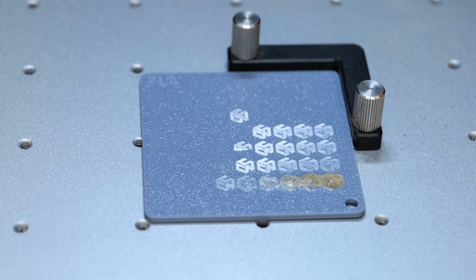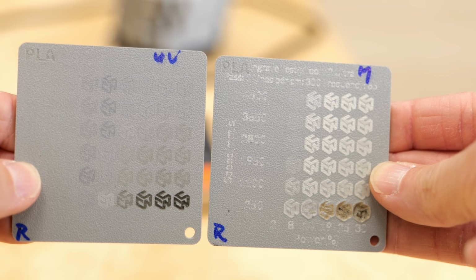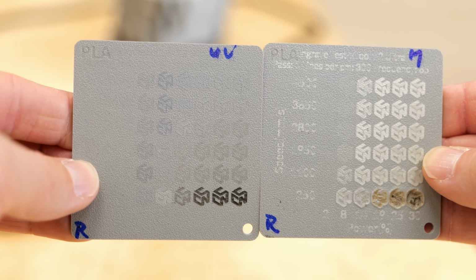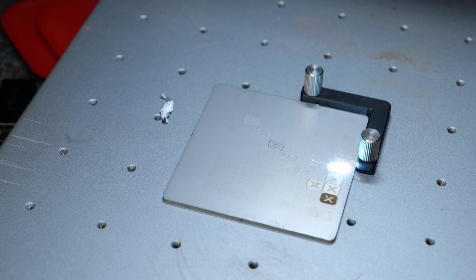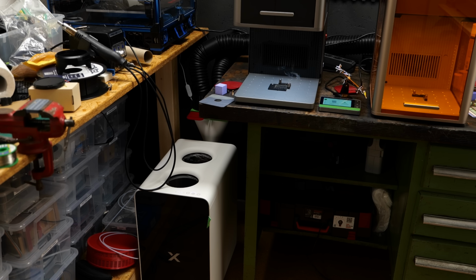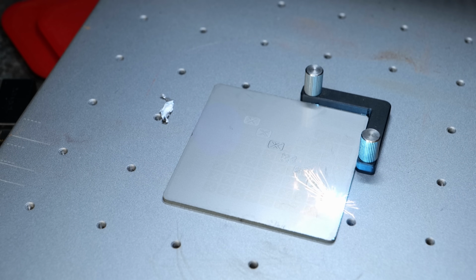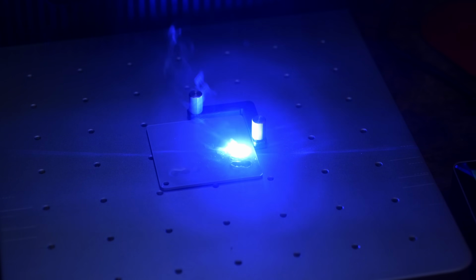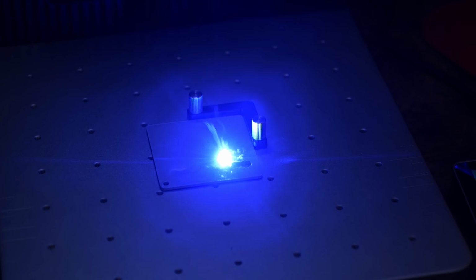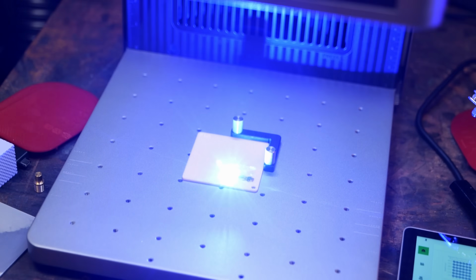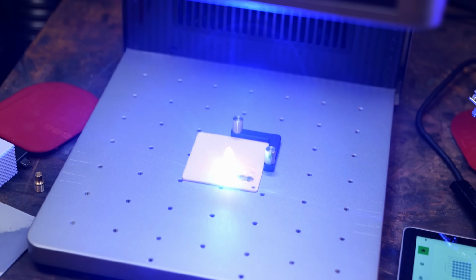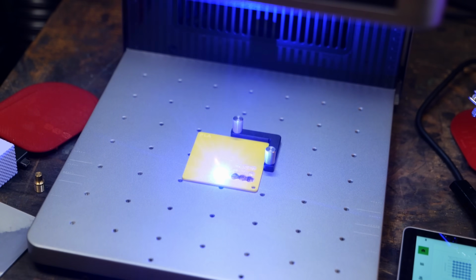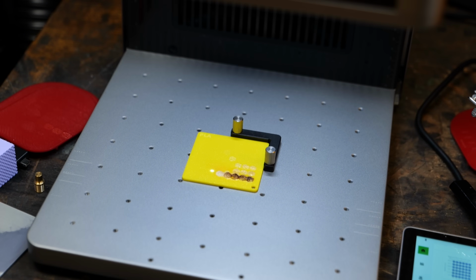The MOPA laser was also very capable, and on some materials it worked even better than the UV laser, but it is clearly more a metal marking machine. And for plastics, the 60-watt version often has way more power than you really need. The big advantage though is the extra control over pulse duration and frequency, which gives you more ways to tune the interaction. The blue diode laser was the least useful for cleanly marking plastics in my test. It can mark or melt some plastics, but the process window was much narrower, and it often produced heat damage before it produced a nice high contrast mark.